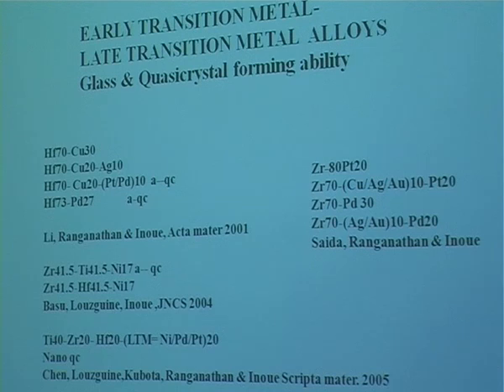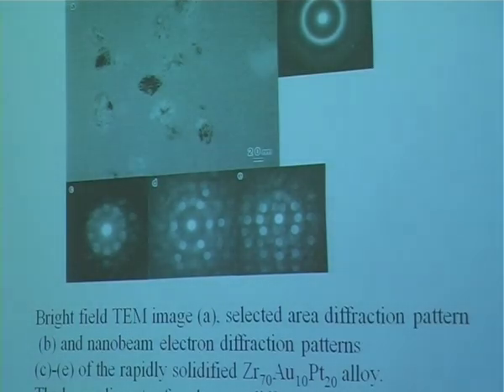In the hafnium copper silver system, which we have published, we find there is a close comparison between glass and quasicrystal forming ability, and we find this in zirconium alloys and titanium alloys too. So the multi-component alloys can be viewed as pseudo lower order alloys. If you have a pseudo ternary alloy, it's a glass. If you have a pseudo binary alloy, it's a quasicrystal, which has been borne out by this. Here it shows, for example, a zirconium gold platinum alloy, which became amorphous, but by heating it we are able to produce small quasicrystals in it.